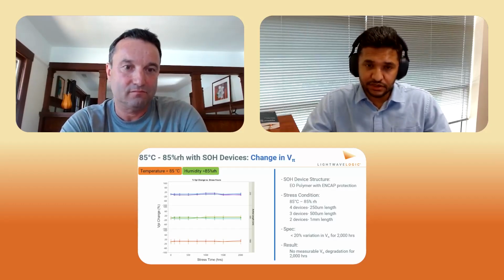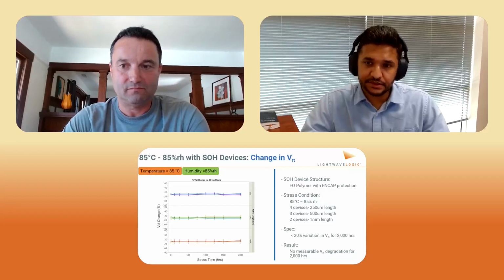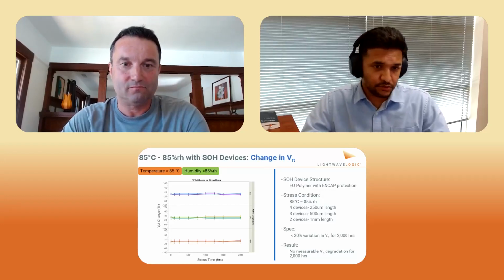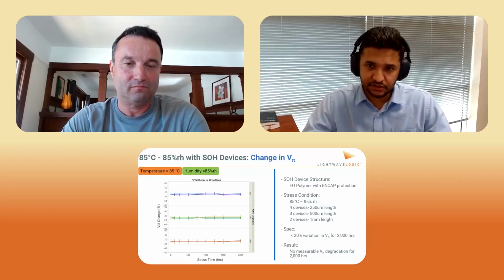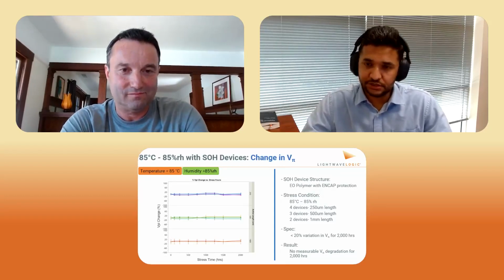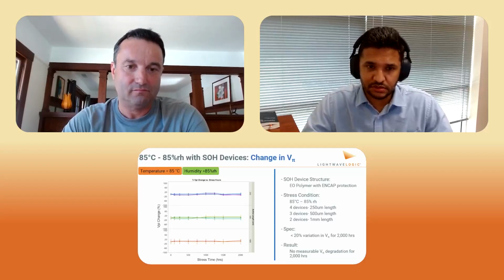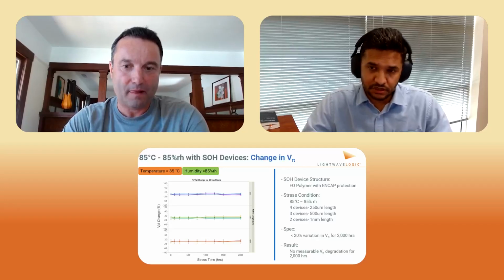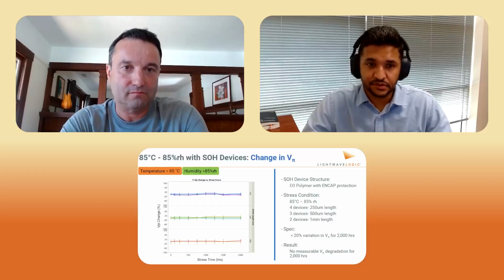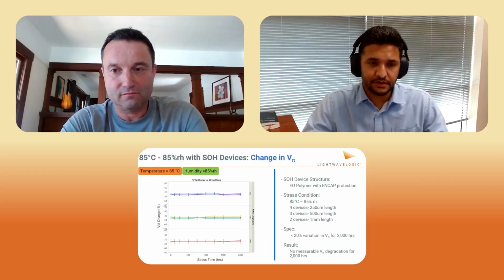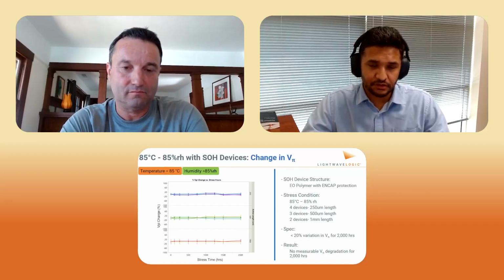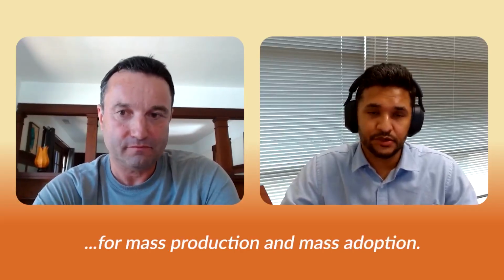And we put not only just one design, but we put three designs in the same chamber to monitor their Vπs over 2,000 hours. And all three designs with three different active lengths show no change in Vπ. So this was a big breakthrough because it was a real condition in presence of oxygen, in presence of humidity, and at high heat, and we see no change after 2,000 hours. So it was really great, and we kind of prove not only to the industry but to ourselves that this technology is ready for mass production and mass adoption.